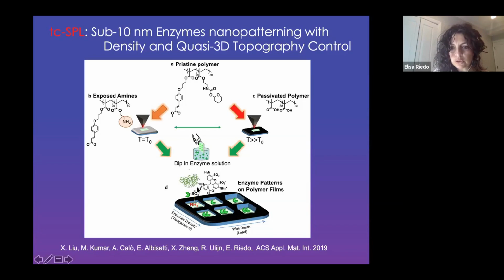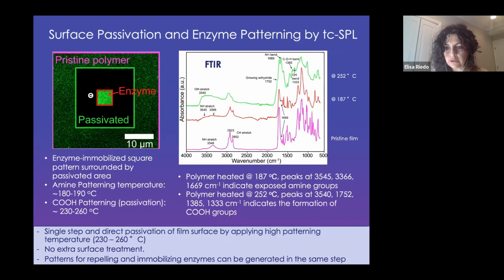So what we are going to do is attach the enzyme by using a sulfonated group, which is negatively charged. So these sulfonated groups are conjugated to the enzyme, and they're negatively charged, and so they are strongly attracted by the NH3 plus group on the surface. Remember, all this is happening in water. This reaction is happening in water and at room temperature. So first you create the amine, and then the reaction of this electrostatic attachment happens in water. So it's very robust, even if it's electrostatic, it's very robust.